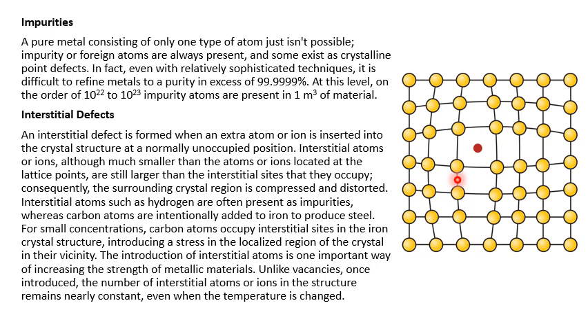Sometimes we introduce this kind of defect to improve mechanical properties. For example, a small amount of carbon is added to iron to increase mechanical properties, as we've seen previously. In this case, carbon atoms go into interstitial sites in the iron lattice, causing distortion and strengthening of the material — increasing the mechanical properties. This kind of defect is different from vacancies: while vacancies increase with temperature, interstitial defects do not depend on temperature.